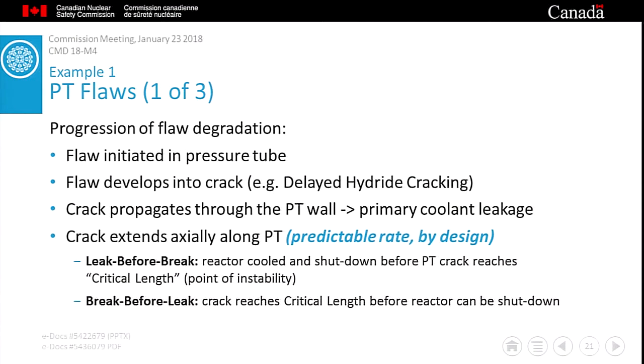And one mechanism capable of doing this is referred to as delayed hydride cracking, and that's symbolized as DHC. Under certain circumstances, this crack can grow through the pressure tube wall, allowing pressurized coolant to leak into the leak detection system. Finally, under specific conditions, it's conceivable that that same through-wall crack could extend along the length of the pressure tube. And at this point, the CNSC defines two possible outcomes. We can either have leak before break, which is the target that all licensees are expected to meet, or we can have a condition referred to as break before leak.